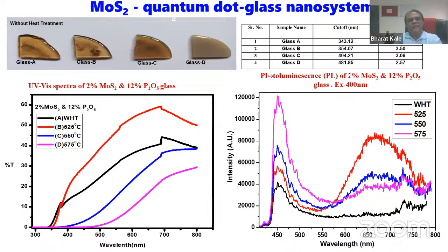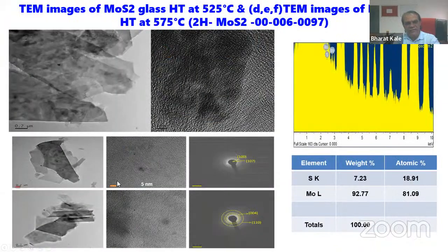Then recently we also grew MoS2 nanoparticles in the glasses. You see here MoS2, very interesting. MoS2 is a plate-like structure. So you see in the MoS2 glass itself, you get the plates of MoS2. Very interesting. We have not done any other applications yet, but now we are going to see what kind of applications we can have with this glass, though the glass is very transparent.